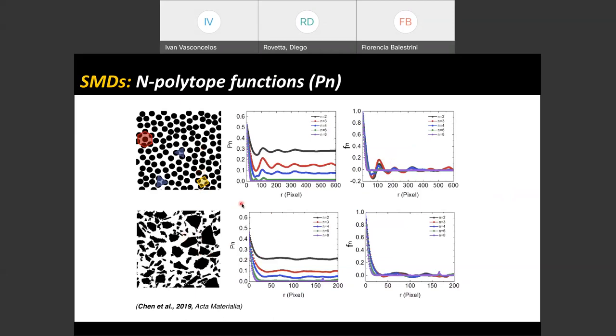Now, like I said, these probability curves all have volume fraction at the origin. And the way they tend to some number at larger distances here depends on volume fraction, actually. So genuinely, it's difficult to compare curves between two materials of different volume fractions. So what we have are these Fn functions that you see here. I'm going to show you equations for them in the next slide. But what you need to see here is that these curves oscillate between 1 and 0.